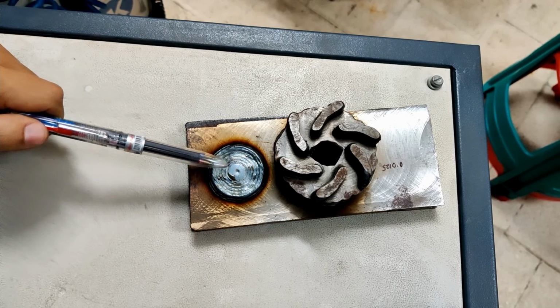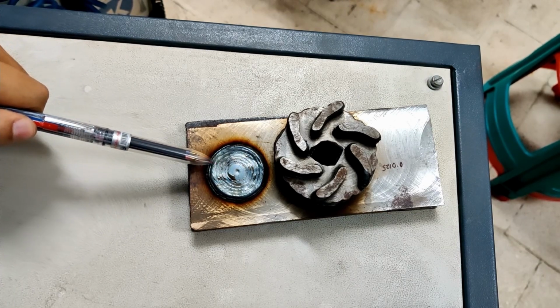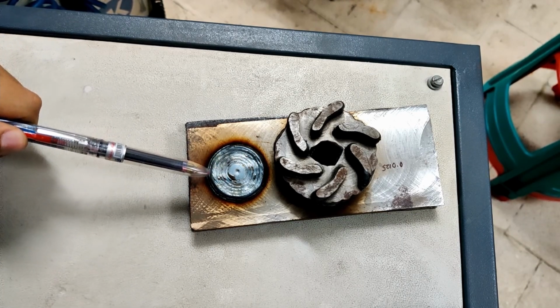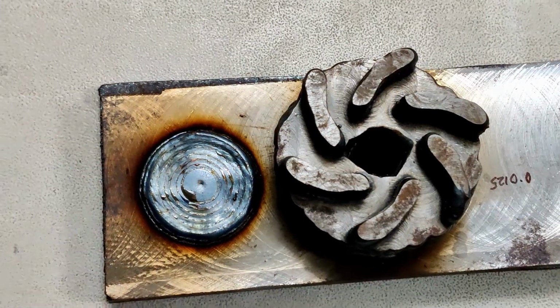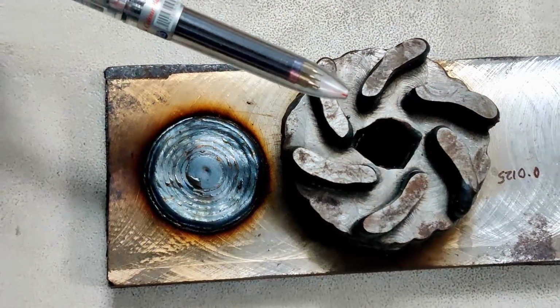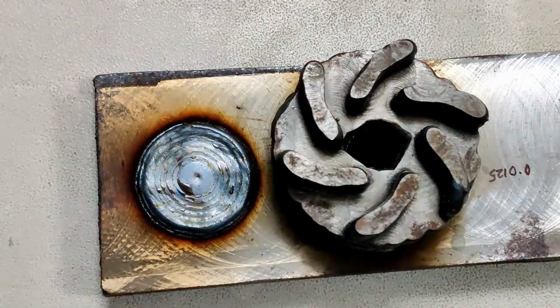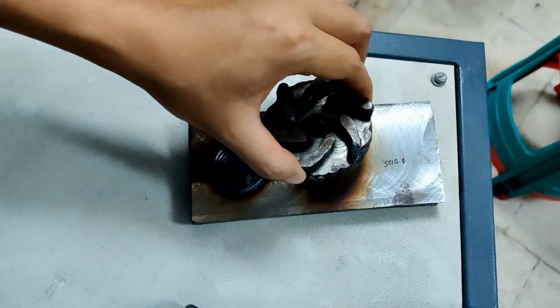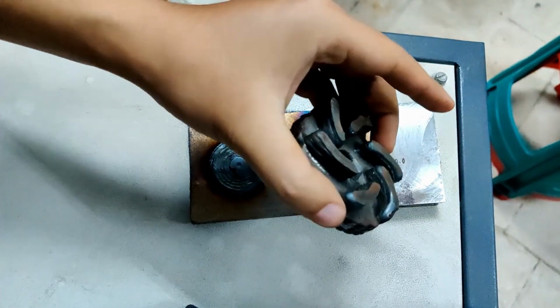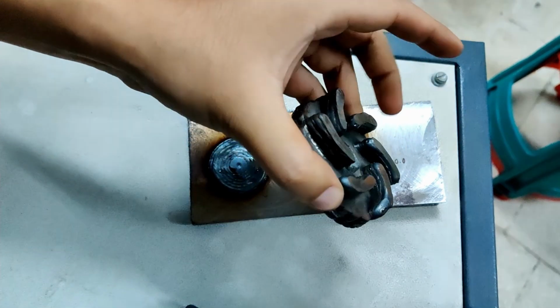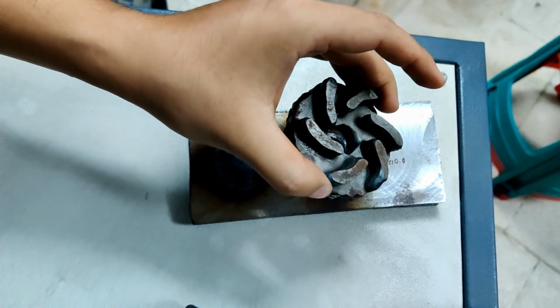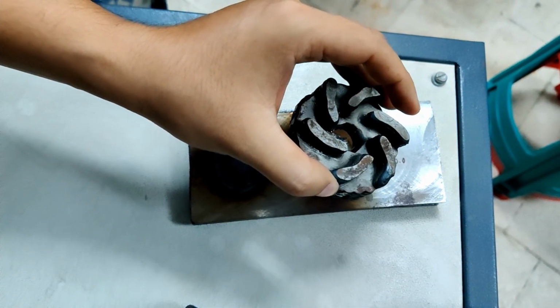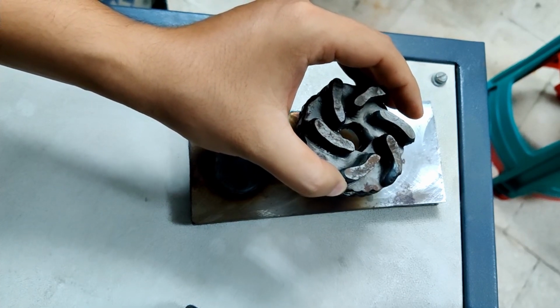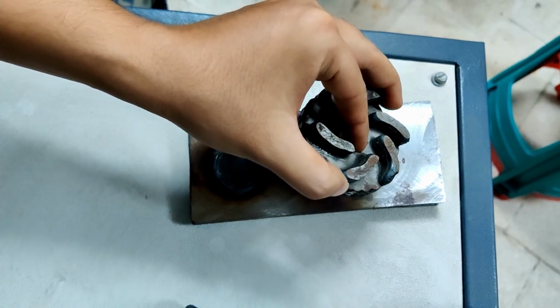You can see it gives a very fine finish, and you can obtain a near net shape at a very fast rate. We have made this impeller using this setup only, and you can see we have obtained a near net shape very quickly. You can see the blades of the impeller also. We have manufactured the object within a time span of around 15 minutes.